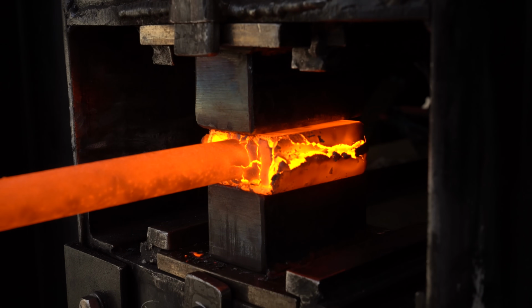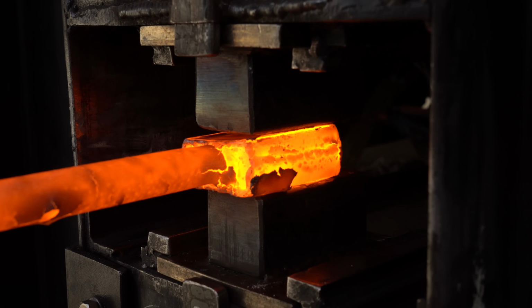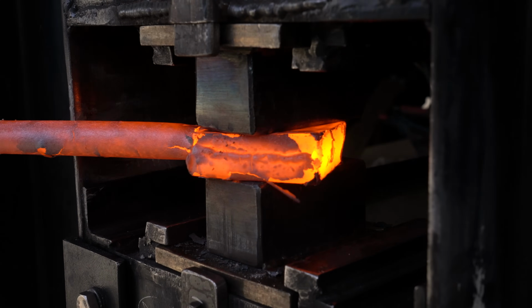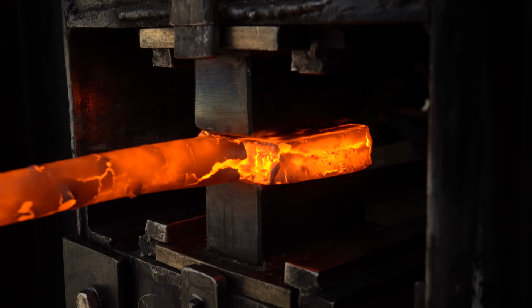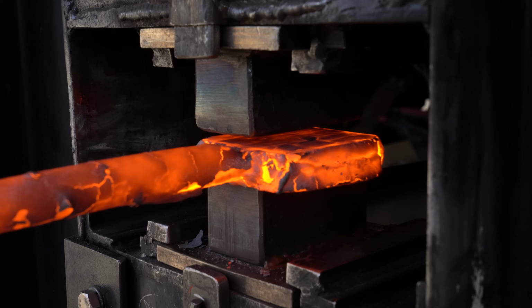Welding the pipe to the canister instead of using that coupling, much better idea. That worked out really well, had no problems. I was very confident on this forge weld, and it went really well.